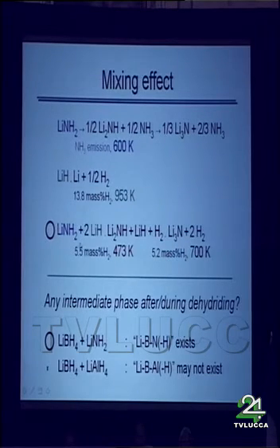I mean, the point is to estimate if there is any intermediate phase after or even during the dehydriding reaction. For example, in the combination of lithium borohydride and lithium amide, there is an intermediate phase like the lithium BNH systems. But in case of lithium borohydride and lithium alanate, there is no intermediate phase. So in this case, a mixing effect may not occur.